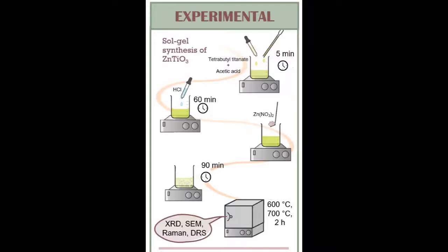For the sol-gel synthesis of the material, we mix tetrabutyl titanate with acetic acid to control the hydrolysis of the titanium precursor. After 5 minutes, we added hydrochloric acid as a catalyzer. 1 hour later, we added zinc nitrate crystals to our solution, which was mixed and heated until the formation of the gel. The gel was thermally treated at 600 and 700 Celsius degrees for 2 hours.